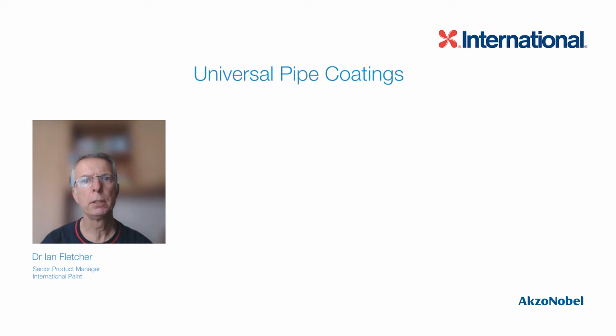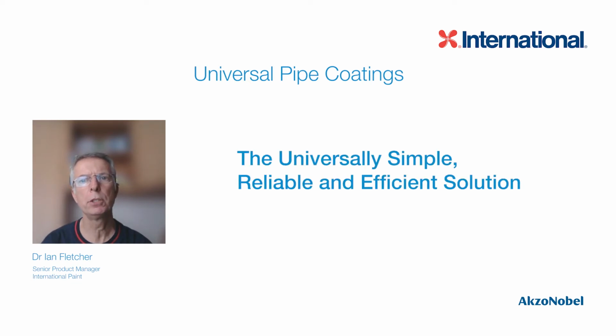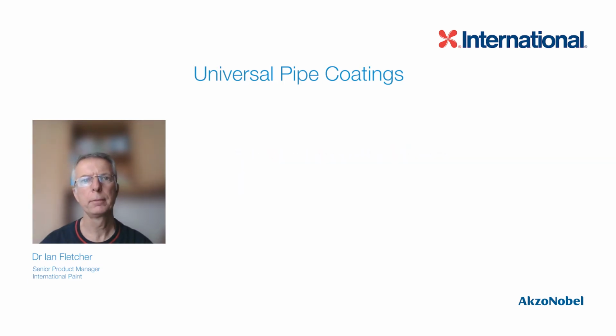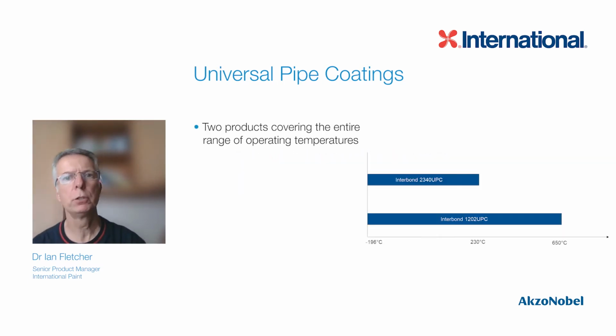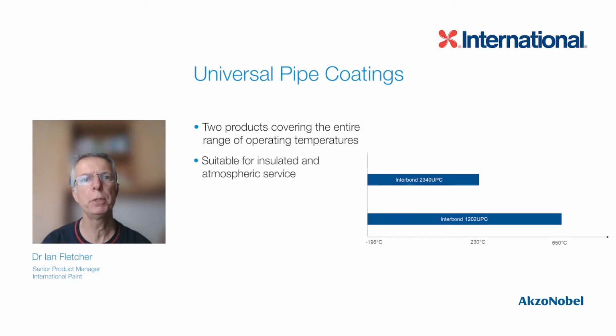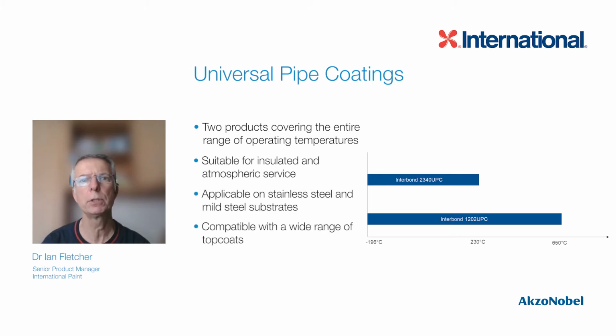To overcome this complexity, we developed universal pipe coatings as a universally simple, reliable, and efficient solution for both specifiers and applicators. The universal pipe coating range, also known as UPC, is comprised of two products: Interbond 1202 UPC for process piping and equipment operating between -196 degrees Celsius and 650 degrees Celsius, and Interbond 2340 UPC for process piping and equipment operating between -196 degrees Celsius and 230 degrees Celsius.